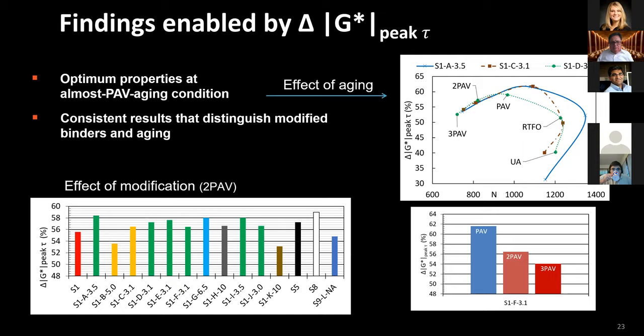At the very bottom, you can see the effect of the modification at 2 PAV and the delta G percentages. So some of that ranking that we saw before, these are grouped a little bit differently, but you can still see the base binder S1 and the binder of the 58-28 without modification, its results as compared to the modifiers. And then at the very right bottom, you can see this is modifier F in base binder S1. And you can see the curve goes down with aging. So the delta G goes down as you age those materials. Those trends were seen across the board for all of the different modifiers in this project.